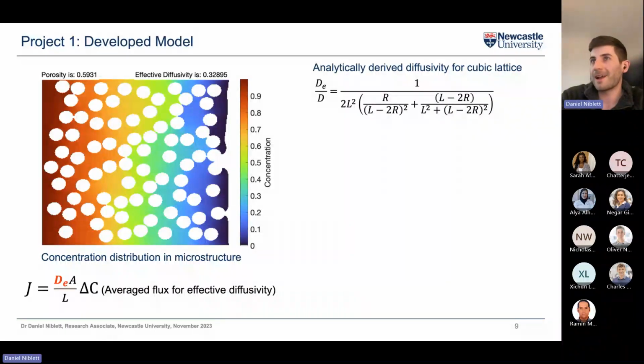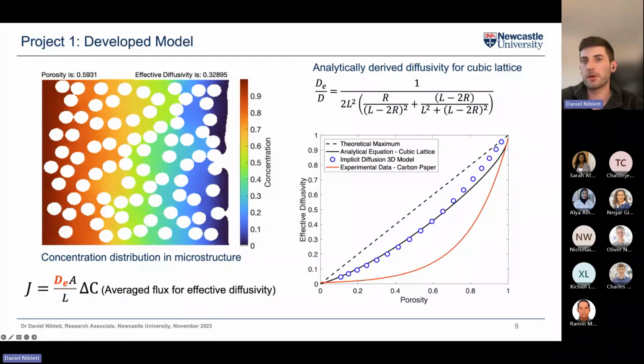And so for those cubic lattices that I described before, I analytically derived the diffusivity for the cubic lattice, which means that we can know what the value should be, so I can test this model I built to see how accurate it is. And so the analytical equation is the black line, and the blue dots are the prediction from this numerical model at a range of different porosities. And as you can see, there's a fairly good agreement between the analytical and the finite volume method that I made in MATLAB. And you can see it's getting close to the theoretical maximum at any porosity, which is the dashed line.